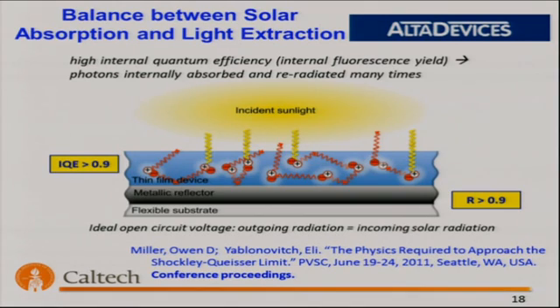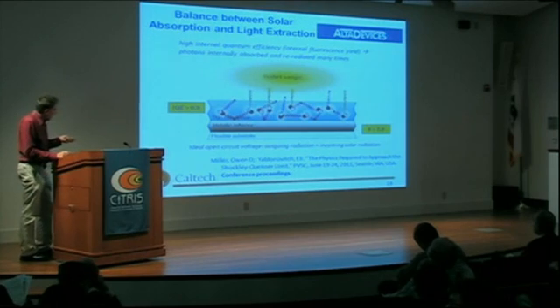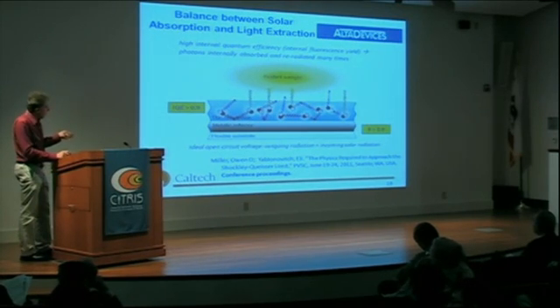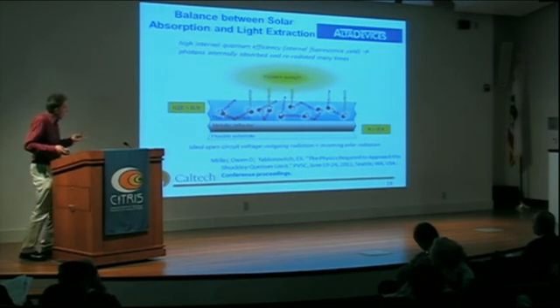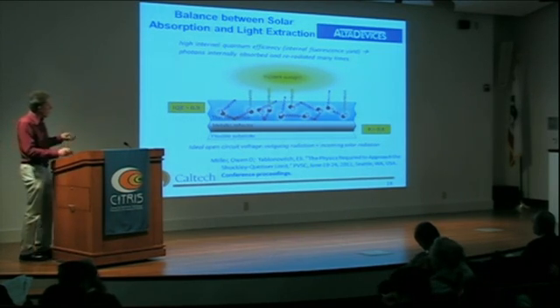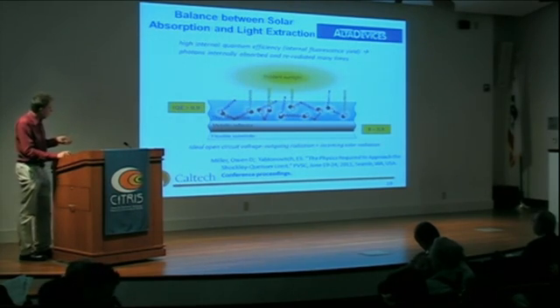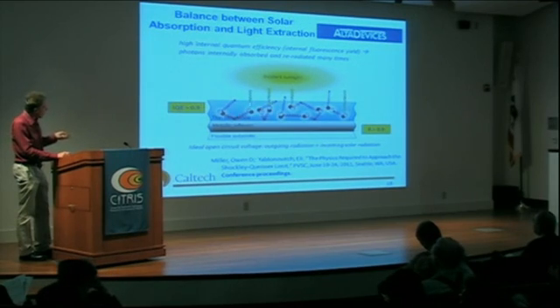So in the circumstance where you have a very, very high internal fluorescence yield or quantum efficiency, plus a very highly reflecting mirror, the photon is recycled many times. It could be as high as 100 times before it's extracted. And Eli recognized that this was an opportunity, and he also recognized that it was very important, harking back to Shockley and Queisser, that it was important to emit the light, that without paying attention to the external fluorescence emission, which is a necessary balance to the absorption, light would not be absorbed in the cell.